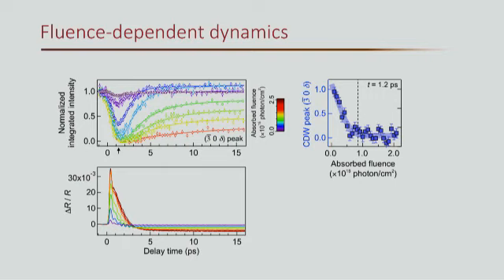So let's dissect together. First of all, you can see there are small wiggles here, meaning there are some coherent oscillations being excited. And we can really see this in delta R over R because it gives us a very good signal-to-noise ratio. Pictorially, that oscillation has many different frequency components, and the most prominent one is the 2.2 terahertz frequency. If you look up the literature, that corresponds to the excitation of the amplitude mode.